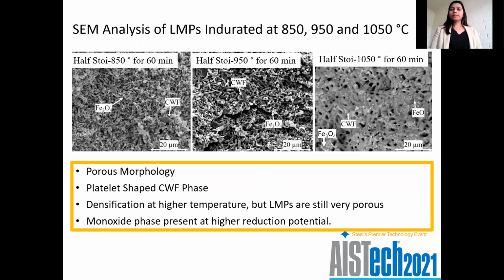These are some of the SEM micrographs of the samples produced using pure chemicals. The LMPs were heated at 850, 950, and 1050 for 1 hour. What we're seeing here is that the CWF phase has a platelet-shaped morphology, and the platelets are interconnected to each other. At higher temperature, we can see they are coming together and getting densified. The whole structure is densified.